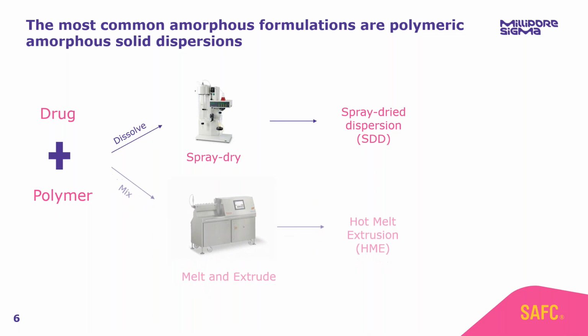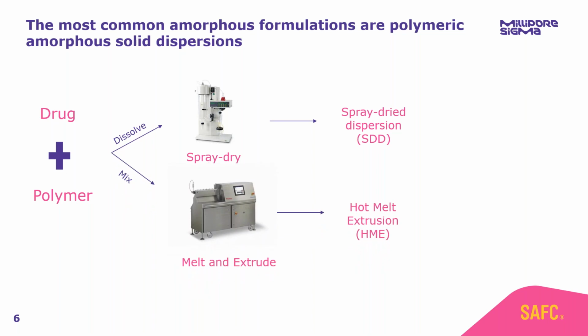SDD. Alternatively, we can take advantage of heat via hot melt extrusion. So we mix, melt, and extrude, and what we get at the end is known as a hot melt extrusion formulation or a HME. Now, the only difference here is the processing method. On a molecular level, these formulations are basically identical.